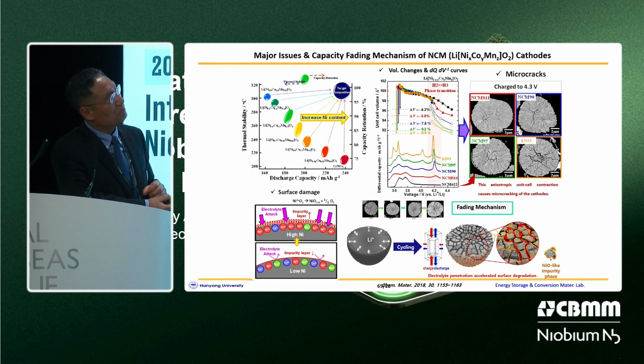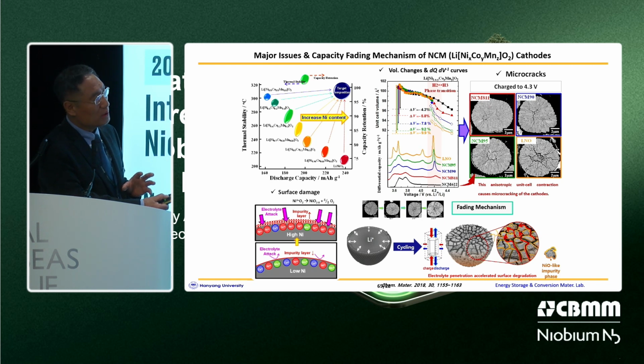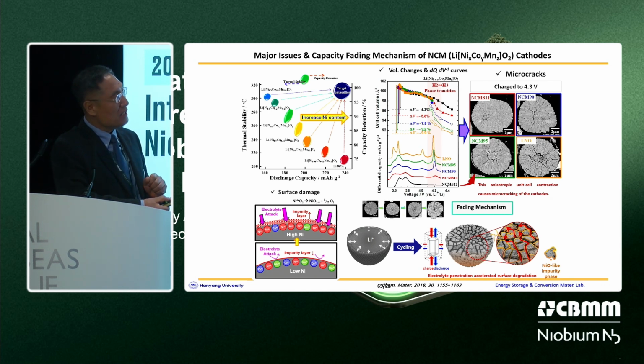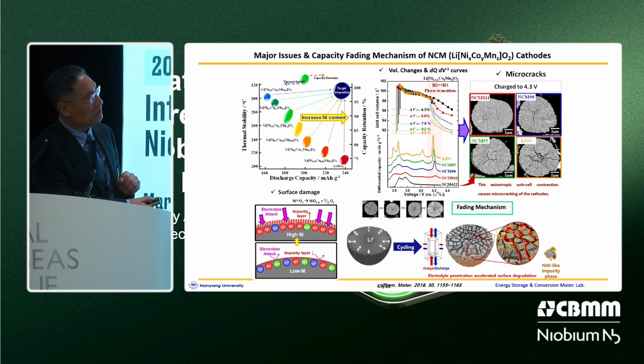To confirm this hypothesis, we observed the cross-section of various different kinds of cathode material after charging to 4.3 volt, fully charged. As you can see, the NCM-811 contains some microcracks in the particle interior only. However, the NCM-90 and LNO cathodes exhibited an increased amount of microcracks, which well propagated to the particle outer surface. And it is very well known that the parasitic reaction of the tetravalent nickel with electrolyte produces a nickel oxide-like rock salt impurity layer on the cathode surface. And with increasing nickel content, the damage increases.